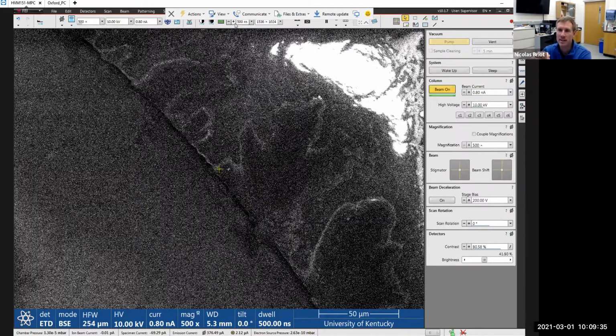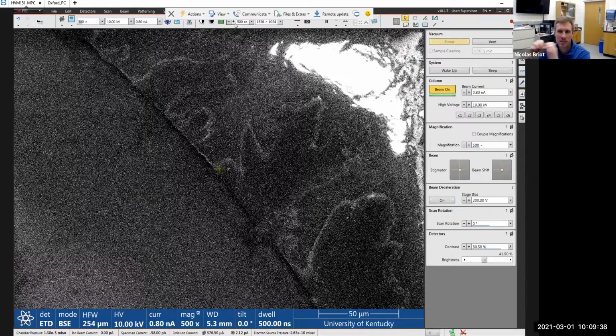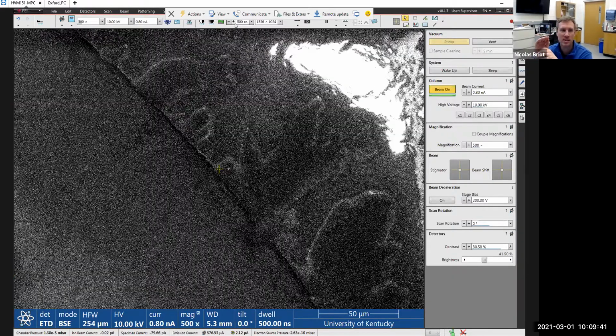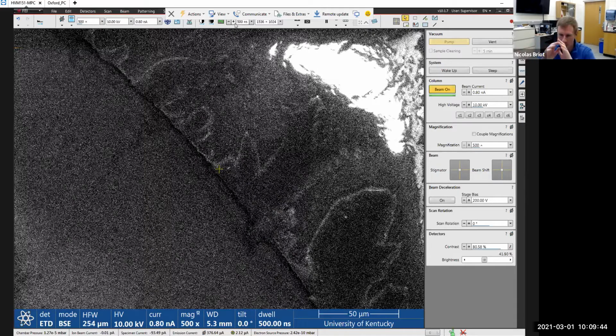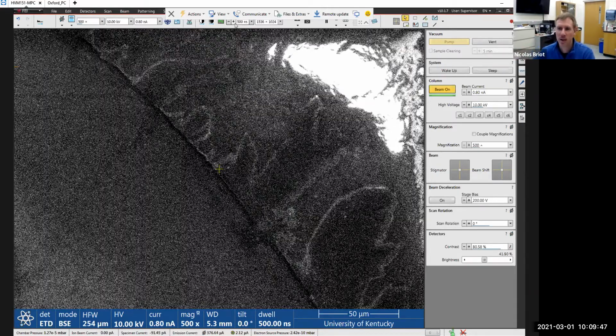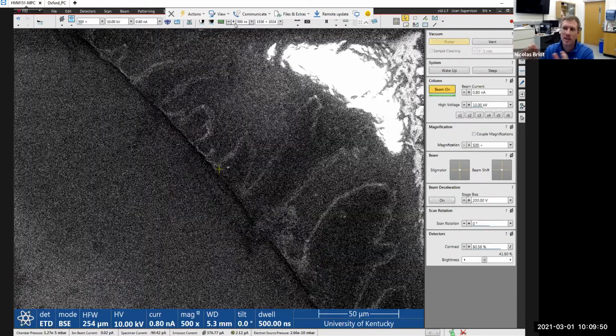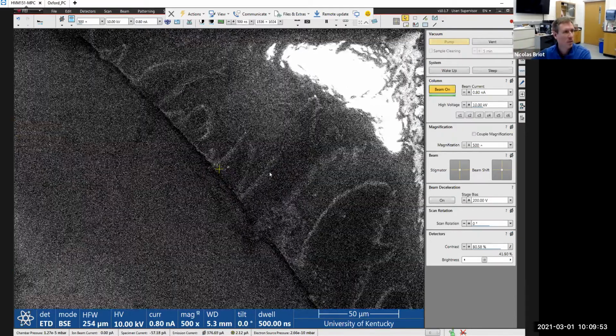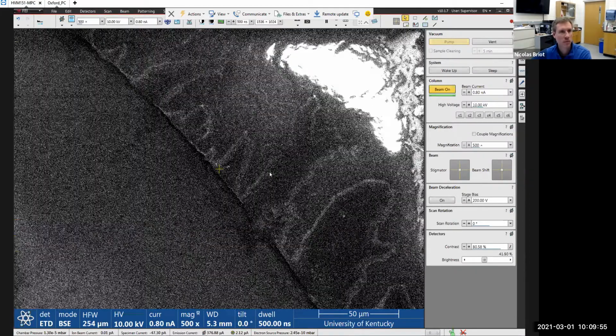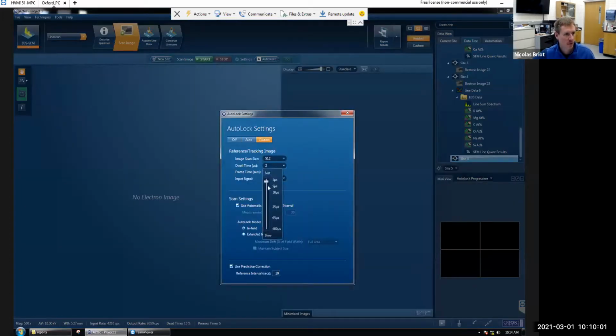It doesn't matter when you do your line scan, if the image is moving. When I started, you started to see a region that was a little higher in potassium. And as I waited, it pretty much started to widen and disappear. You didn't see it, but as soon as I stopped, I looked at the image and it was actually shifting. So what we can try to do is use some drift correction techniques. Once you get into those problems, it's a little tricky. So let's see if it's responsive to this technique.